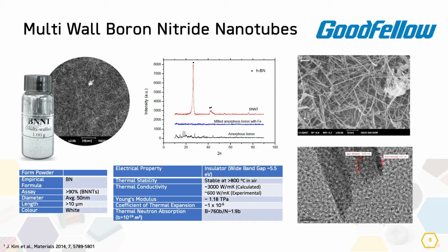So we have calculated experimentally the thermal conductivity, and it has been shown that it's 600 watts per meter Kelvin, which is very, very important. Also by SEM analysis and TEM analysis, we have defined the layer distance and the wall thickness of these boron nitride nanotubes. Further purification can also be done, and the most important part is that these boron nitride nanotubes can have a purity of 90%, which is, I would say, the only material with such a purity commercially available worldwide, and that's why it's very important.